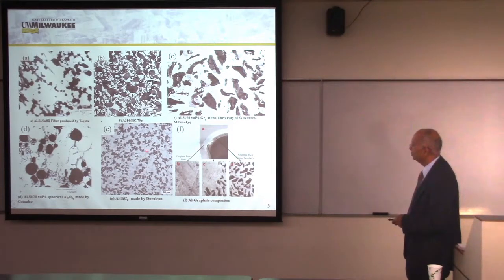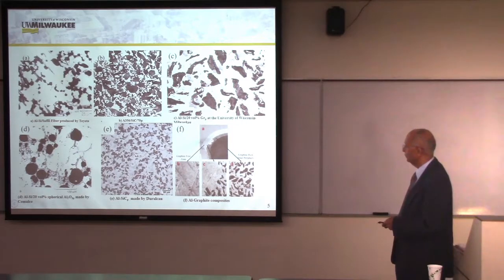This microstructure is spherical alumina dispersed in the matrix of aluminum alloys. This microstructure is 20 volume percentage with dark silicon carbide particles embedded in the matrix of aluminum alloy. This material has been used for brake rotors in many cars that I will show you a little later.